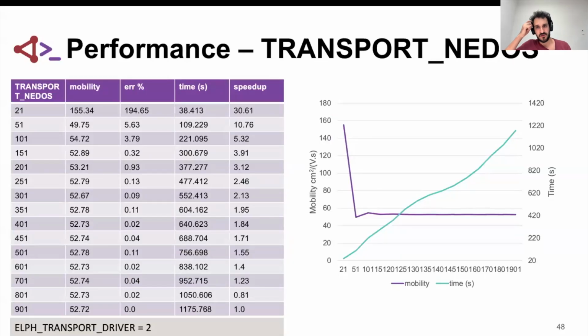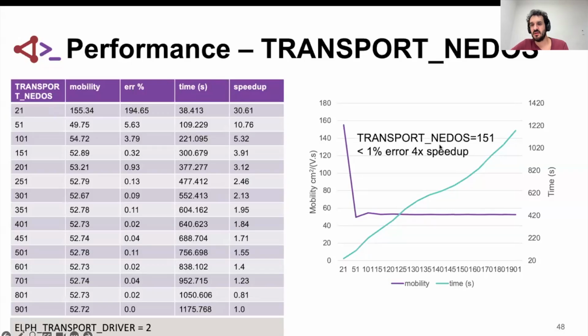Another INCAR tag is TRANSPORT_NEDOS, which I mentioned in the case of Gauss-Legendre integration, so ELPH_TRANSPORT_DRIVER = 2. I show different values of TRANSPORT_NEDOS on the left, and we can see that beyond 250 points, the mobility doesn't change anymore. So why should we continue increasing the number of points if we are only increasing the computational time without changing the final value of the mobility? In this case, the optimal setting would be to use 151 points for the energy integration.